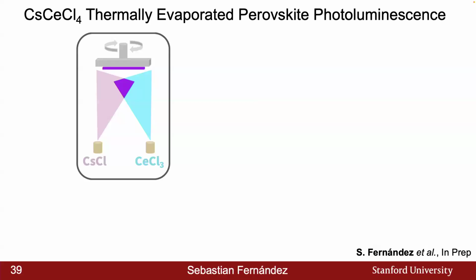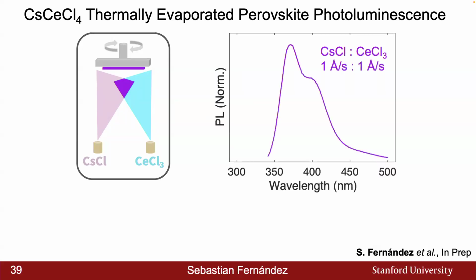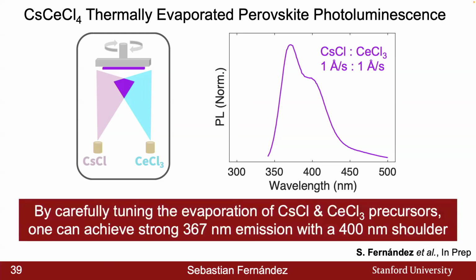So encouraged by this, encouraged by the results from the lanthanide double perovskite class system, and because I was responsible for a lot of setting up the perovskite thermal evaporator within the lab, we then looked at thermally evaporating this cerium-based system first in this dual source evaporation scheme as shown here. And so by carefully tuning the rates and the ratios of these materials with respect to one another, we're able to then, from the photoluminescence of this material, take a dramatic step forward into the ultraviolet spectrum by now having a peak at around 367 nanometers with a shoulder at 400 nanometers. Now taking a very dramatic step into the UVA spectrum and seeing what we can do from here.